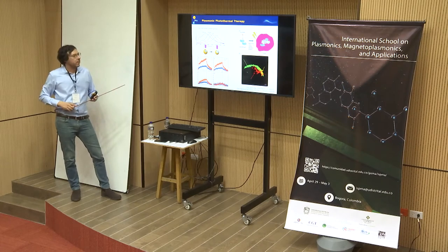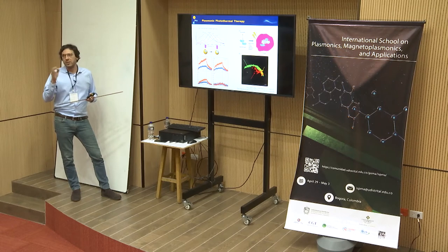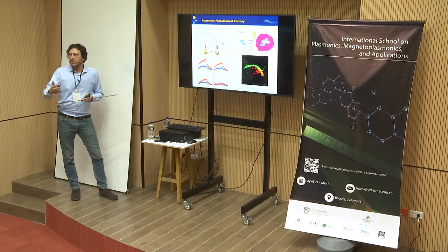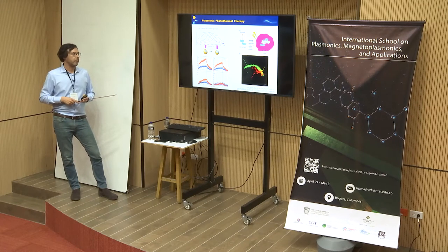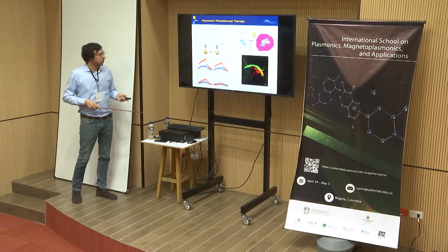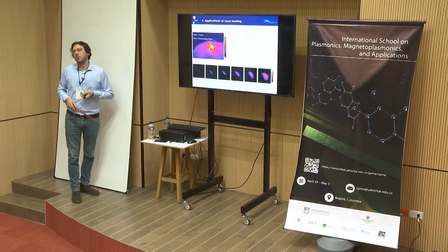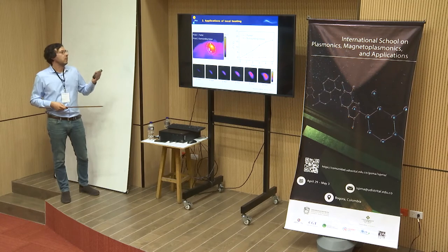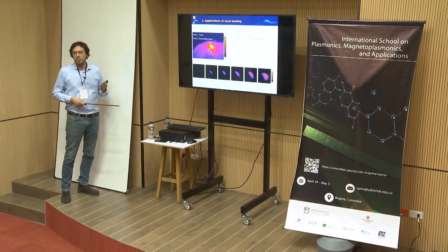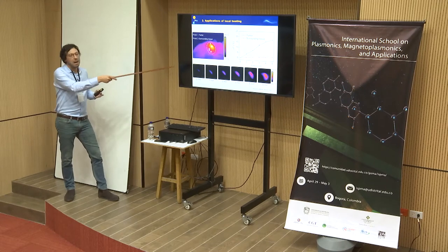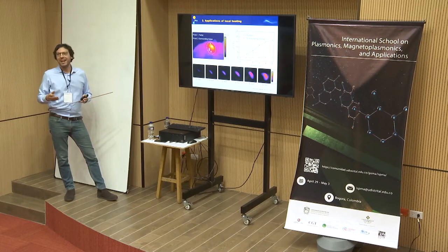And that's why the most famous nanostructure is this nanoshell produced by the Halas group, because if you get the gold particles, usually these would resonate around 500 nanometer or 530 nanometer. Otherwise, if you get this core shell structure, you can really shift the absorption of the particles towards the red wavelength range, so you can play with this photothermality. Basically, what you do is just injecting these particles into the body, and through a recognition system based on receptors, basically you can target your particles in a specific region where the tumoral tissue are expressed, and therefore you can heat up locally the nanostructure, as you can see here, for example, in your mice, or in this case, of course, the final user would be us, and so you can really, let's say, treat your tumor.